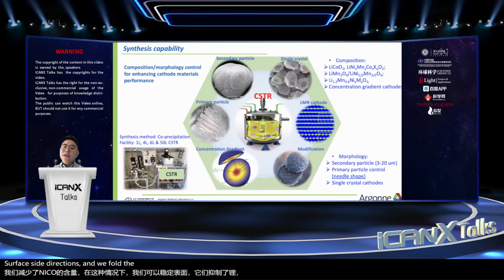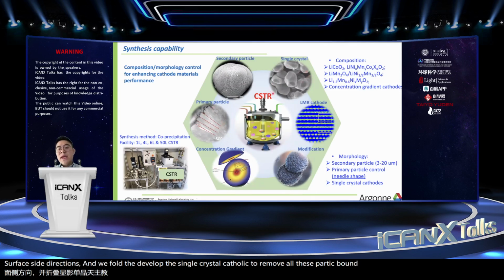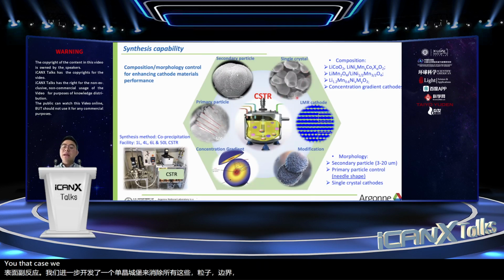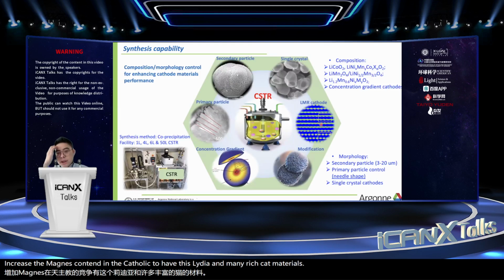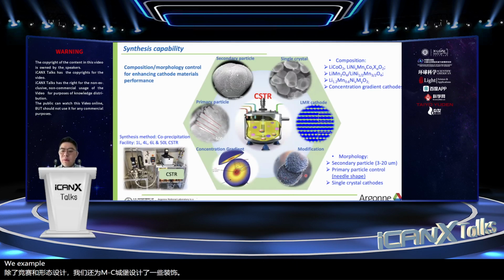And we further developed the single crystal cathode to remove all these particle boundaries. In that case, we can suppress the particle cracking. And also to lower the cost, we have increased the manganese content in the cathode to have these lithium and manganese rich cathode materials. Besides the composition and the morphology design, we also developed some modifications for the NMC cathode. For example, we developed a coating technology we call the ALD coating using the gas phase.